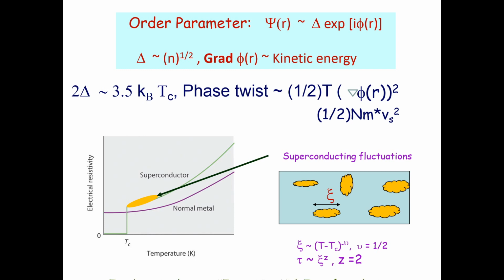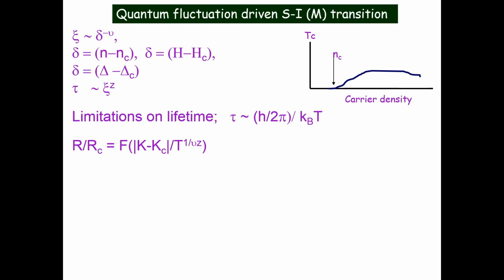Now if I push the temperature down, in 2D there are more complications, so let's not talk about that. But if I go down to the lowest temperature, then there are no thermal fluctuations. What drives the transition? These all happen because of the quantum fluctuations in the system. And we can again write down this correlation length, which goes as delta to the power minus nu, and delta is actually the distance. What you are doing is playing with one of the parameters of the Hamiltonian, varying that, and that causes the transition.